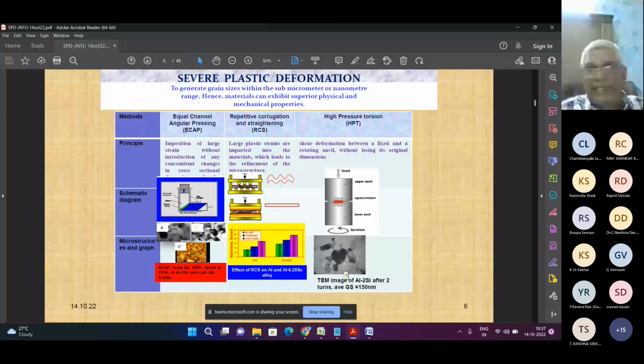What we are thinking is, in our lab we have made one ECAP die, which has a 25 diameter by 125 length. We could process with this one. But the die is a split die, not a single die. Why? Because with a single die, if any problem comes, it is very difficult to machine inside the die. So we have made a split die, done experiments, and it is working very nicely. Another process is called repetitive corrugation and straightening, that is the RCS process.